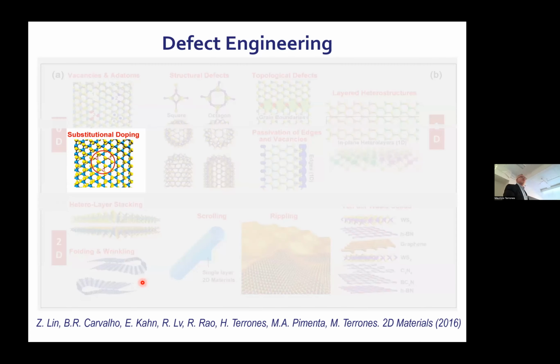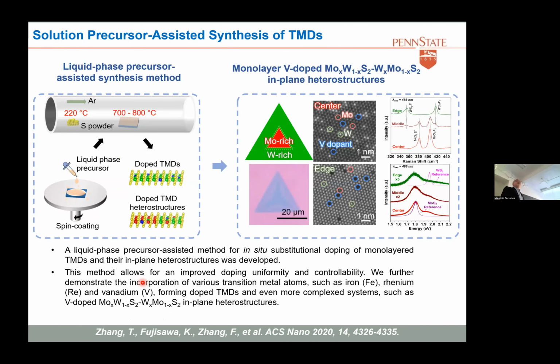So I will go with the substitutional doping. That means in situ, or in the synthesis, we replace the atoms, and then we try to dope or to make an alloy of the system. So I will go through how we do it, and it's a very simple way to do it. The idea of the synthesis that we're applying is a synthesis method that people can try everywhere. I think the field advanced very quickly in the area of TMDs, also with graphene. When people were able to grow graphene with CVD, that was a big thing, right? Because everyone could grow. Of course, Scotch tape mechanical exfoliation was also easy.